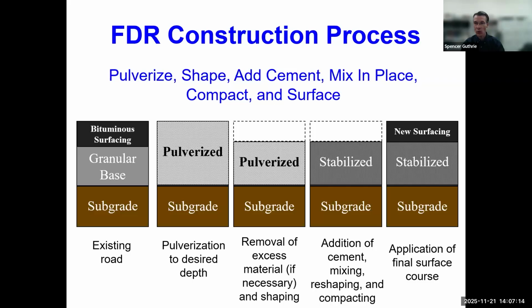The fourth step shows stabilized base material now, perhaps with cement or another appropriate stabilization agent. And once that's been appropriately cured, then we can put a new surfacing, which might be either asphalt or concrete, or in some places in the world, we might just put a double chip seal on top of the stabilized base material. And that's a far lower expense than placing a new HMA or Portland cement concrete. So let's look at the construction procedures.